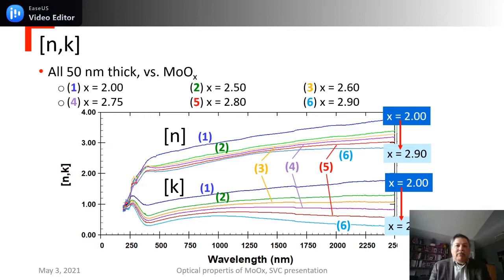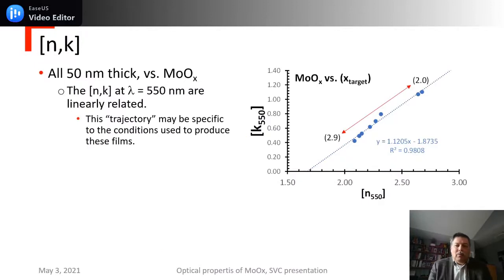Now, when we put all of that together, this is what it looks like. As promised, the N is greater for low oxygen and becomes lower as oxygen increases, and the K becomes lower as the oxygen increases. Now, one of the things I will discuss in a slide that is coming up shortly is what I call a trajectory of the N and the K. So I'm picking it at a certain wavelength. 550 is in the middle of our eye's sensitivity. And this trajectory kind of defines this material and defines how we made this material.